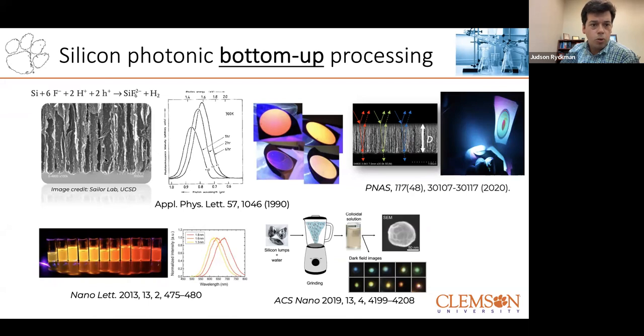The process consumes holes. So if you use an N-type wafer, you need to illuminate. If you use a P-type wafer, you do not. And you're left with some of these byproducts, but a very nice, porous and high surface area material. This has lots of applications beyond photonics. There's a lot of biomedical applications, drug delivery applications, but we're especially interested in the photonic applications.